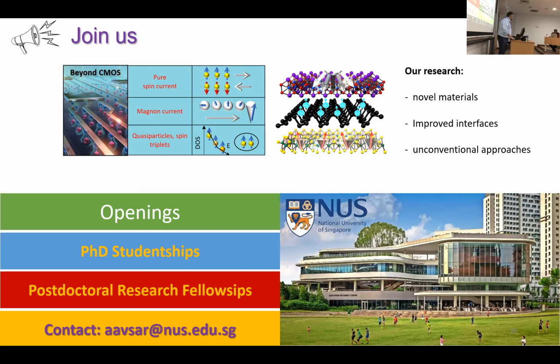So in one of your slides, you showed that for the spin valve measurements, there was a spin injector and a spin detector. What's the maximum length that you have set? The maximum length for black phosphorus is around 6 micron. For graphene, in the state-of-the-art device, one group published from Germany, they could see up to 30 micron. But their devices were also 4 or 5 micron of separation, but they calculated that it should last up to 30 micron.